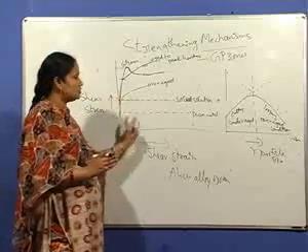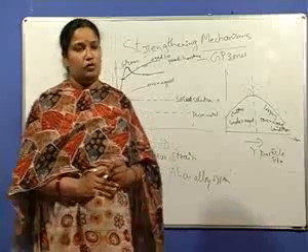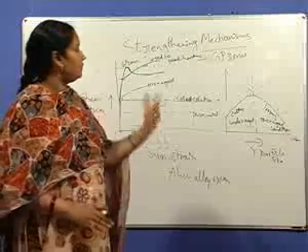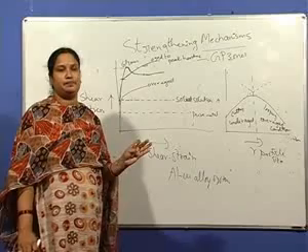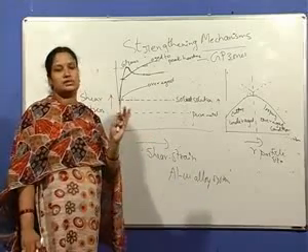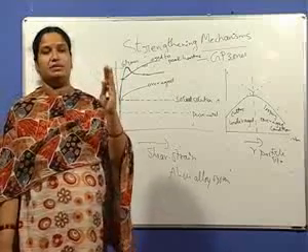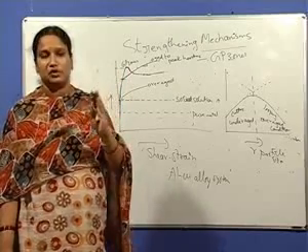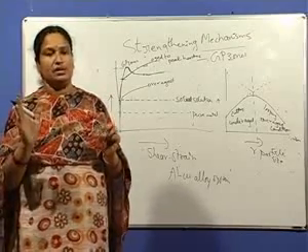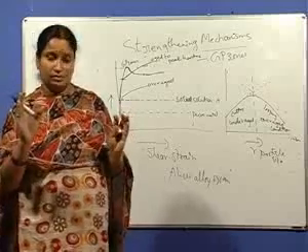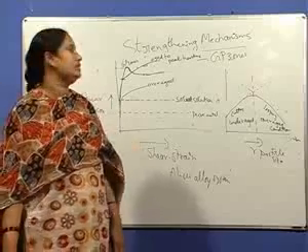So this is the stress strain curve for the case of aluminum copper alloy system for various stages. From this graph, the main point that is clear is that the cutting mechanism lowers the strain hardening. The yield strength is higher for the cutting mechanism, but the rate of strain hardening is lower. For the looping mechanism, the yield strength is lower than for the cutting mechanism, but the rate of strain hardening is higher.